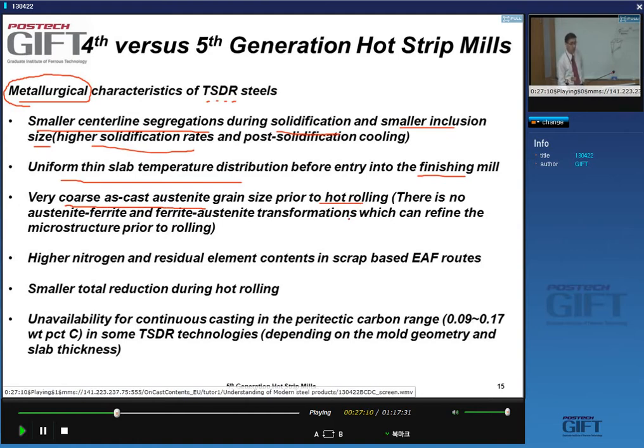that enter the finishing mill. Because you don't have austenite to ferrite and ferrite to austenite transformations, which will refine the microstructure. You see, this slab, when it's cast, it goes through transformation, and when you reheat it, it also goes through transformation. So you refine the microstructure. When you do the roughing, you get rid of the as cast microstructure. So that's not available in this case. You directly roll a product that is as cast.